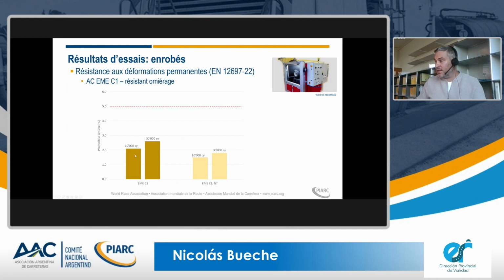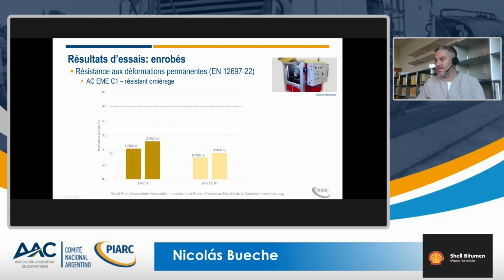And you can see that both asphalt mixtures, the warm mix on the right-hand side and the hot mix, are much below the limit values. It means that we do not have any rutting susceptibility issue, this for the hot or the warm mix asphalt.